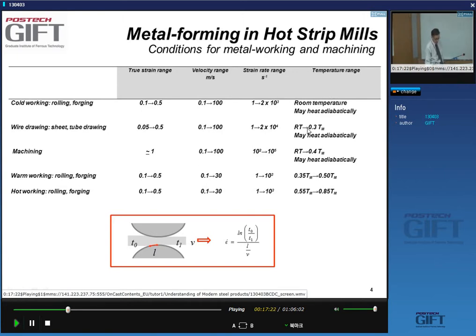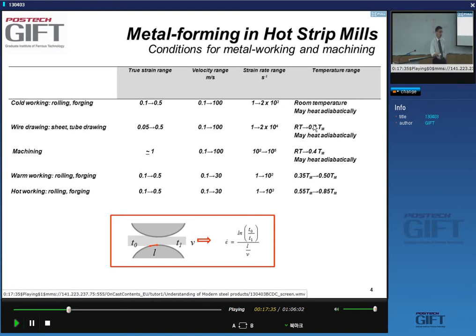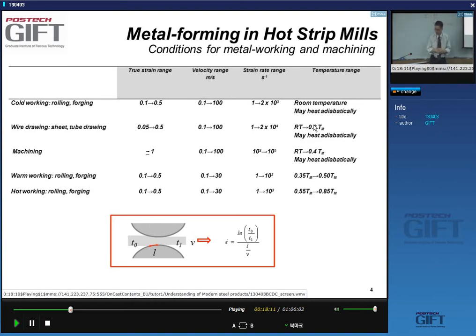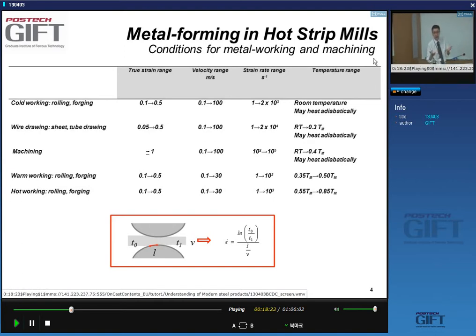About temperatures: cold working is obviously at room temperature. But when you deform a material, especially when you deform it a lot, most of the energy you supply gets transferred into heat - about 90% of the energy becomes heat. The other 10% becomes lattice defects and dislocations. This means temperature will increase, and if there is no removal of heat you get what's called adiabatic heating of the material. There are materials where deforming at even very low strain rates will increase the temperature by 100°C.